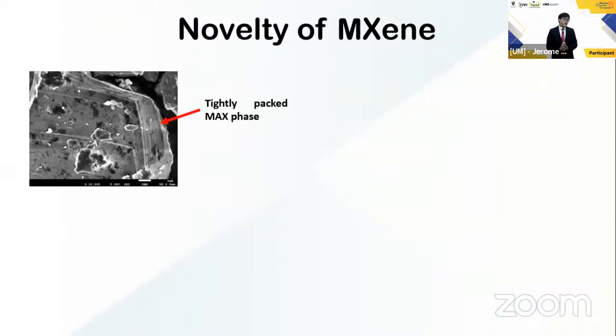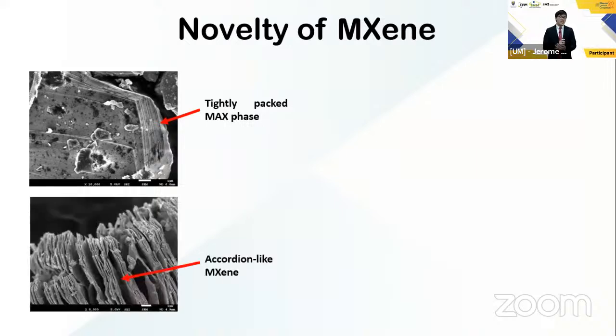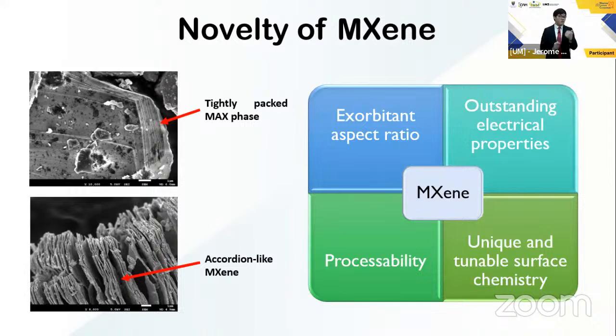The scanning electron microscope image here reveals the morphology of a MAX phase, and we can observe a tightly packed bulky crystalline structure. And after etching the A layer, we can see prominent interlayer spacings between each MXene nanosheet. This is a structure very much sought after in 2D nanomaterials because we can probably tell that they have an exorbitant surface area to volume ratio. And the transition metal nature of this MXene also endows it with amazing electrical and mechanical properties.